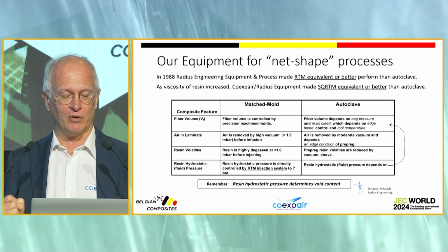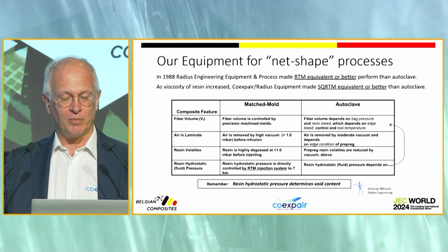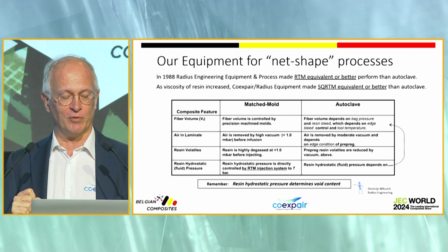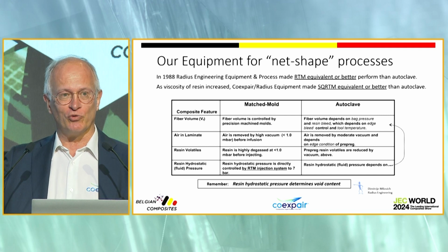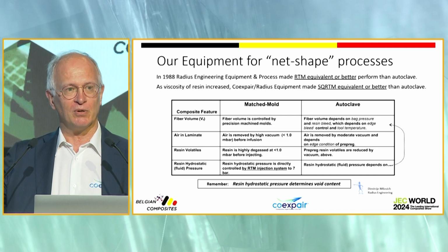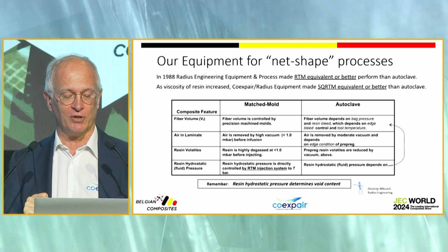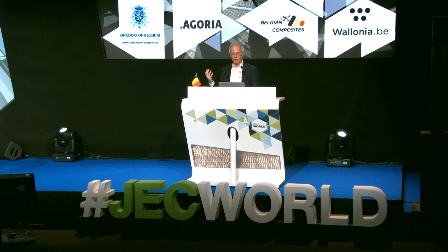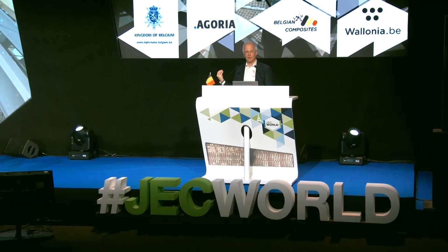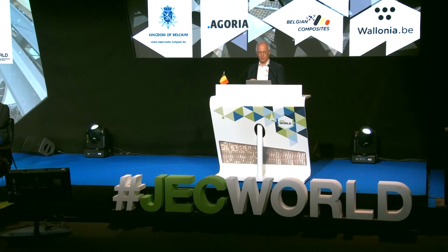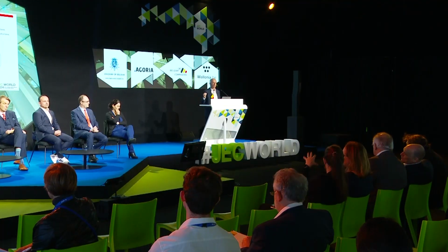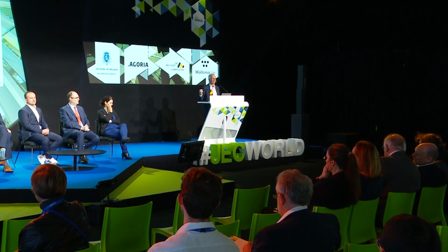And with a closed mold, the fiber bed pressure is controlled by the pressure of the press. The volume fraction is directly controlled because you have a 2-side mold, so the gap and the thickness of the part is frozen. The resin volatiles, we can highly degas the resin and we can control the vacuum in the mold. So compared to autoclave, we want to be in control of the key parameters that the scientists say you have to be in control of if you want to make a good composite part.